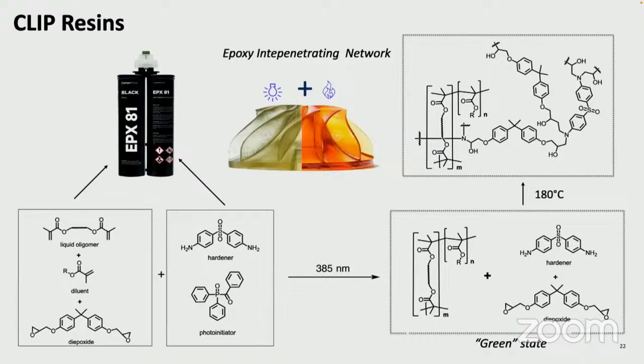So we have free radical chemistry, a photoinitiator, and classic free radically polymerizable monomers. Think about it as 10 to 15 volume percent of a UV curable component. And then we have classic step growth polymerization components, shown here with an epoxy, a diepoxide and a diamine, with a certain pot life. We knew no one ever went into this approach because the printers were historically too slow, and these step growth chemistries would prematurely gel. We're printing 100 to 1,000 times faster. We knew we had a window of operability to combine both step growth and the UV curable systems.